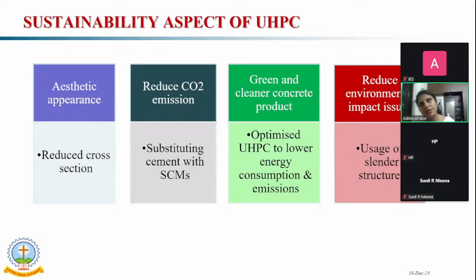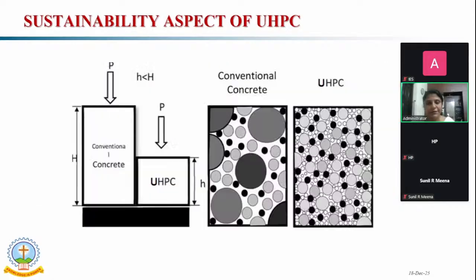In our study, we have considered alcofine or ultrafine slag, GGBFS, and silica fume. Then, as I said earlier, we can reduce the cross section of the structure. If you are considering conventional concrete, the UHPC application mainly comes in the case of girders. If you are considering the depth of the girder in the case of conventional concrete, that depth of the girder can be reduced by using UHPC, since our strength is too high.